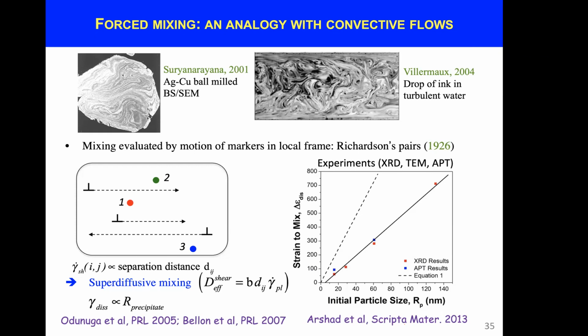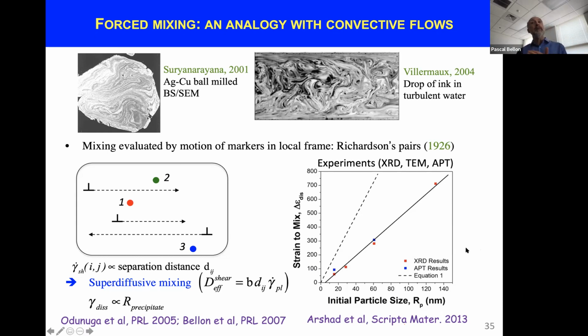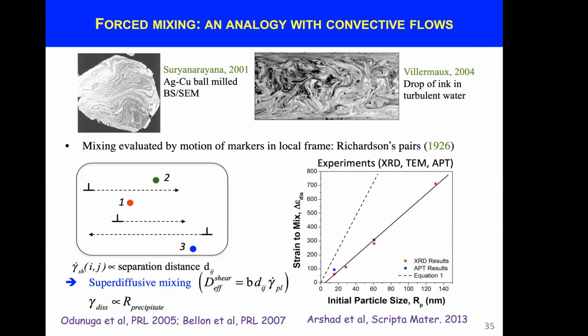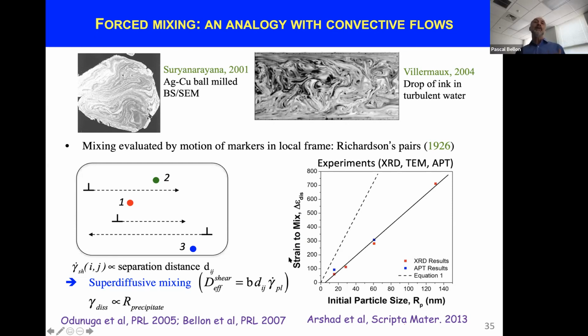It's a direct result from that super diffusive mixing and the equation that was introduced by Richardson. On the right hand side, we tested that numerically. We used copper silver again. We did a heat treatment to start with different precipitate sizes. We used X-ray diffraction and atom probe to identify the strain that was required to dissolve those precipitates. We obtained the strain by performing high pressure torsion experiments, because then you can quantify the strain. And this super diffusive mixing, this is equation one, should have been the dashed line here. And experimentally we measured that straight line.